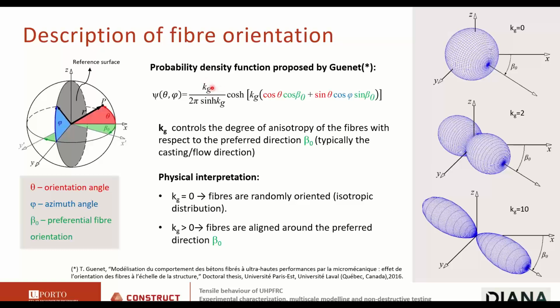So, the physical interpretation of this. If you put Kg equal to 0 here, this means that the probability density function will have a constant value no matter the fiber orientation. This can be represented here at the right using these figures. What do these figures tell us? The surface is defined by this function, and the value of the function is the radius that connects the origin of the reference system to the surface. Okay, so here you see that no matter the orientation of this radius, this vector, the radius is constant. So we have here a sphere, okay, constant radius.